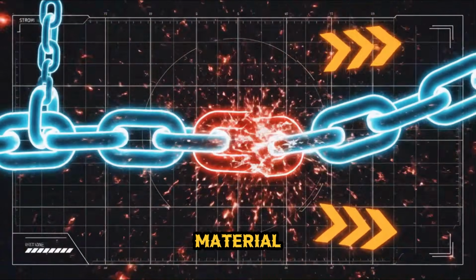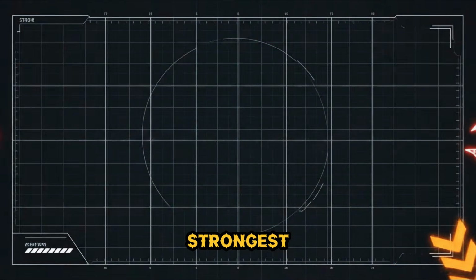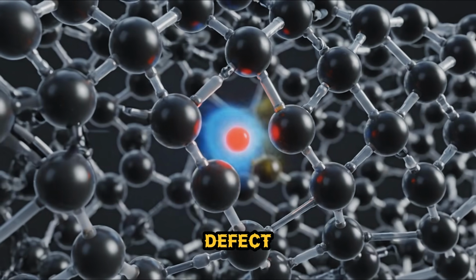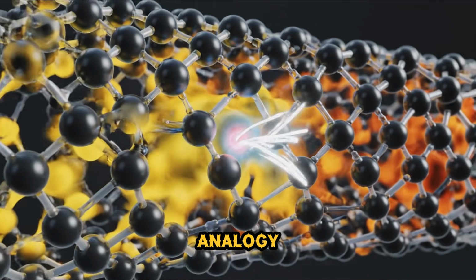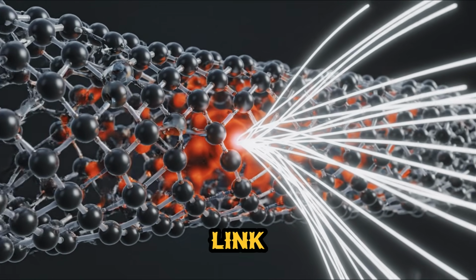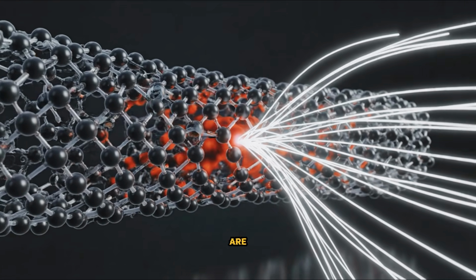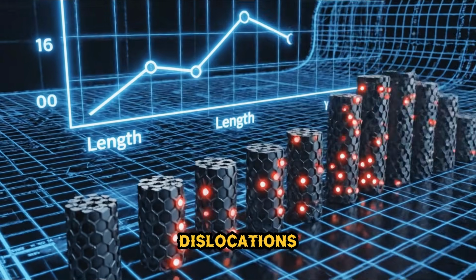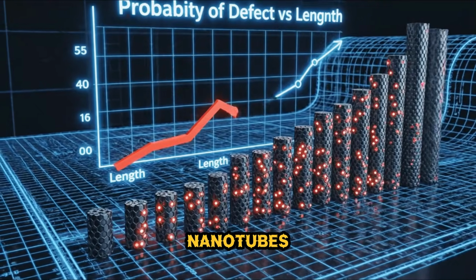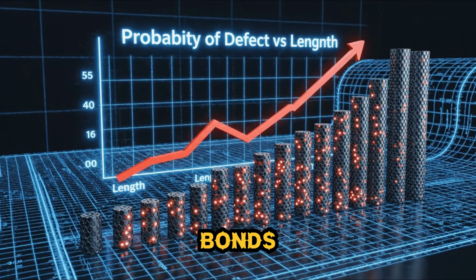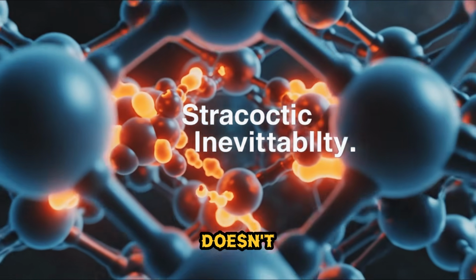The strength of a material is not determined by its strongest bonds, but by its weakest defect. Visual: chain analogy animation, breaking at the weakest link. In steel, defects are grains, impurities, and dislocations. In carbon nanotubes, defects appear during growth: missing atoms, misaligned bonds, uneven chirality. One missing atom in a nanotube doesn't just weaken it slightly. It creates a stress concentration that propagates like a crack.